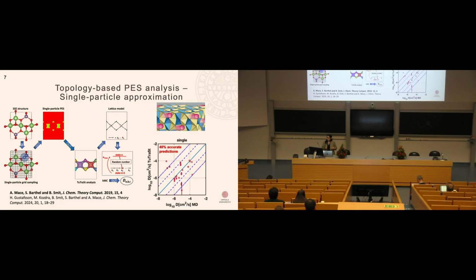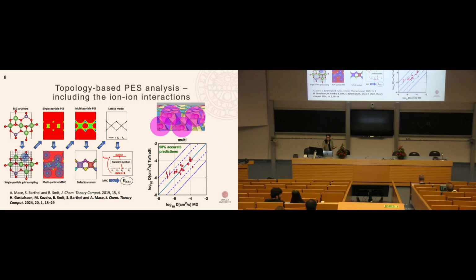But when I moved here to Uppsala and started to look at electrolyte materials, and I tried to apply this approach to ion diffusion in ceramics, the results really did not look very good at all. And this is since a single particle model fails due to the strong ion-ion interactions. So we then proceeded to correct this by adding an extra Metropolis Monte Carlo routine, where we load our three-dimensional energy space with charged particles, our lithium ions basically, and allow them to run a Monte Carlo simulation within this energetic space, where the ions only interact with each other with the Coulomb interaction.